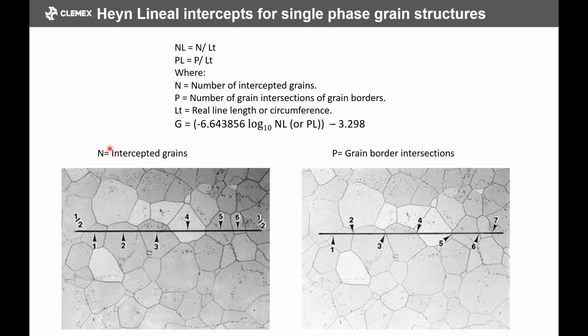So in this case, the formula here would take into account the N and L, which is what we have at the top, right? So N is the number of intercept grains, which is what we have here, and we count the grains depending on the line. And then you make the measurements, or you could use the grain border intersection, which are the segments of the lines. Instead of having counts, you have segments, and you end up with an average segment length, which you put into the formula here, and then you will have the grain size measurement.